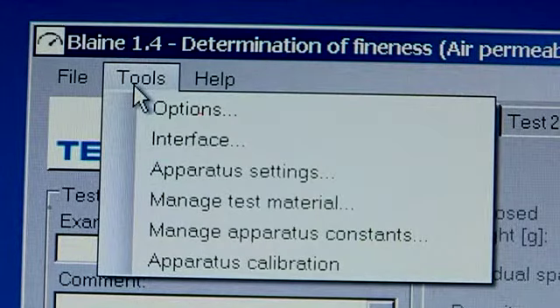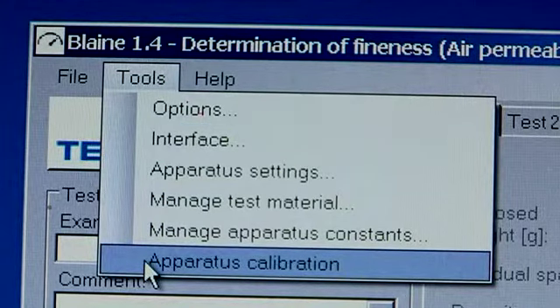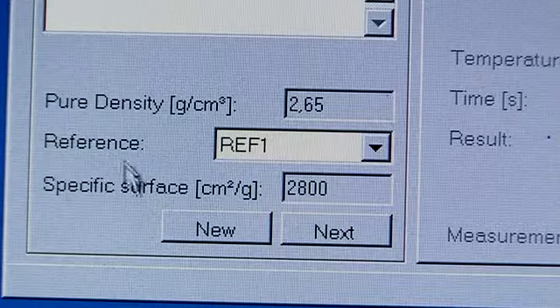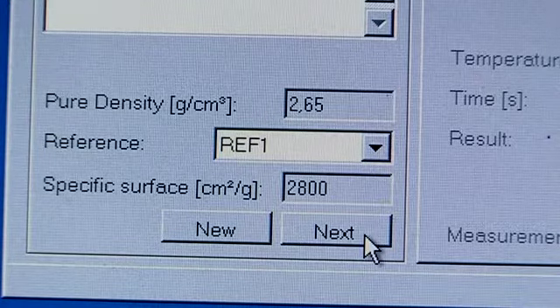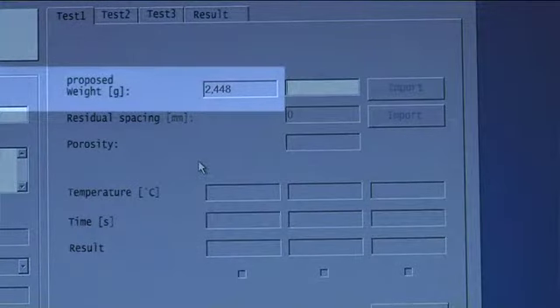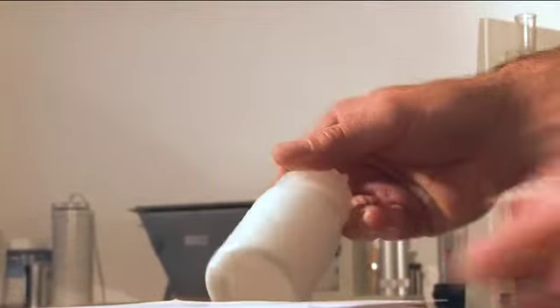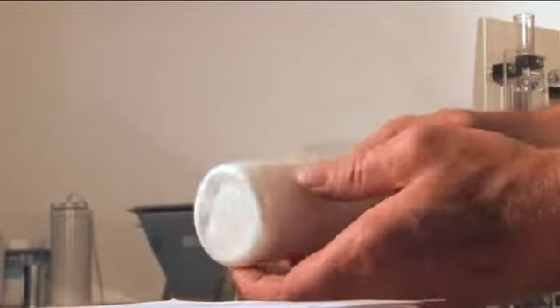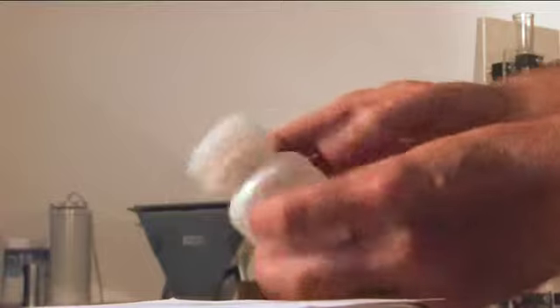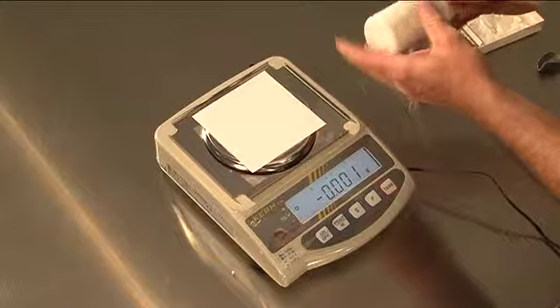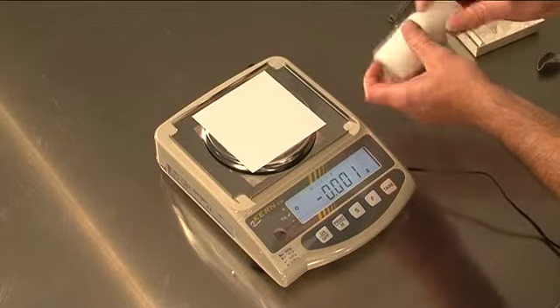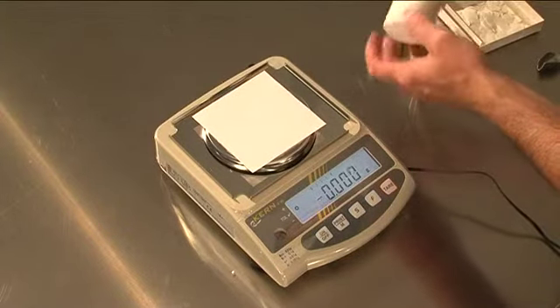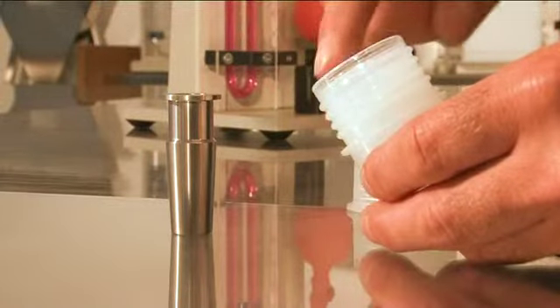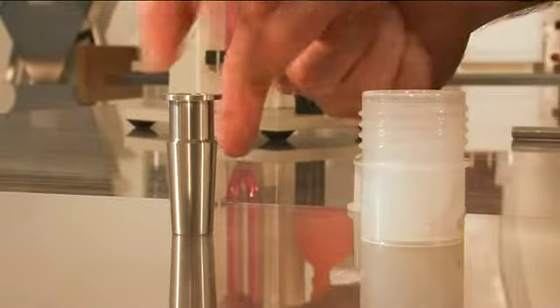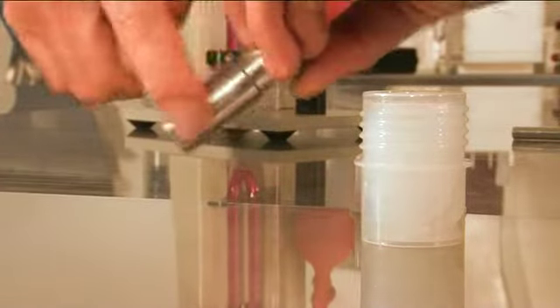Now click on the menu item Tools, Calibrate Apparatus Constant in order to determine the various apparatus constants for the previously entered reference substances. From the already entered parameters, the computer calculates the sample weight. As a preparatory step, the selected test substance is shaken for at least 2 minutes in a bottle with a screw top in order to dissolve any agglomerates. The vessel is then left to stand for 2 minutes. Subsequently, the powder bed is stirred with a clean, dry rod in order to evenly distribute the fine particles. Lightly grease the tapered exterior of the permeability measuring cell in order to guarantee that the U-tube is airtight.